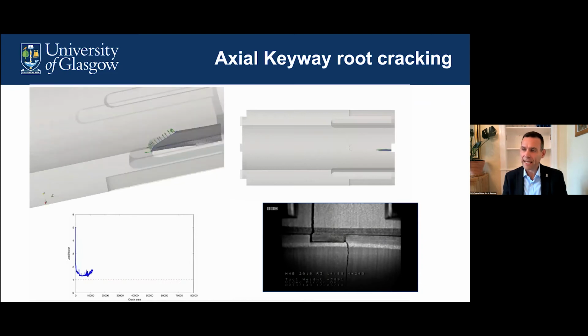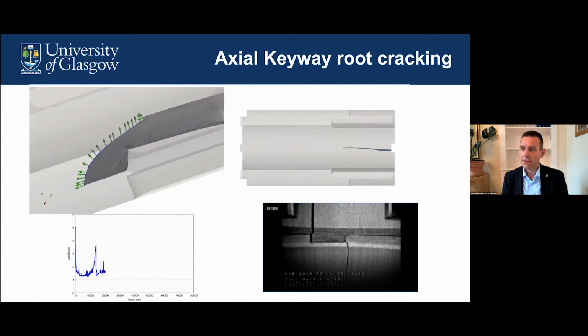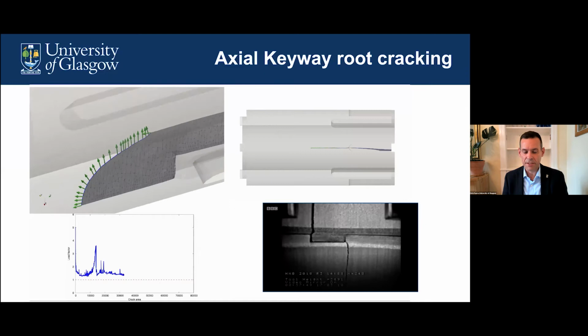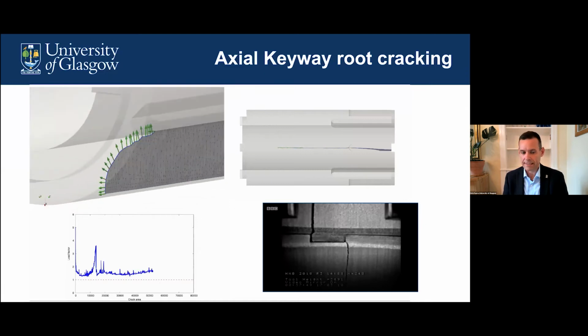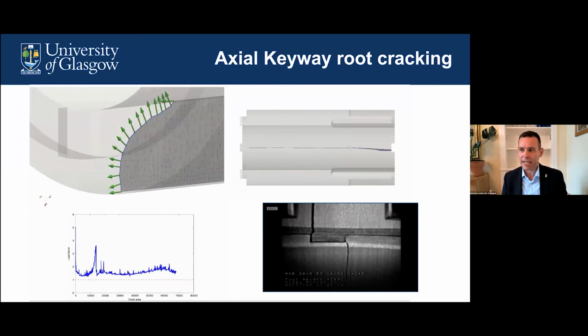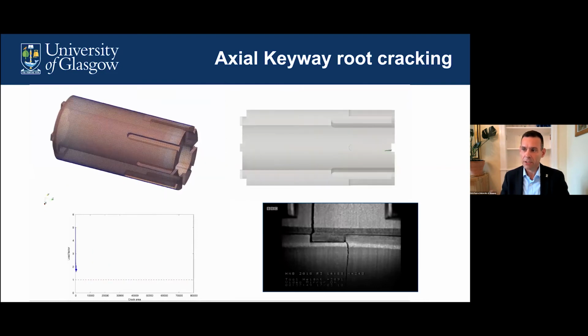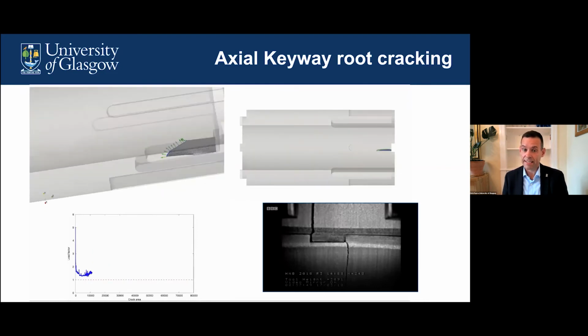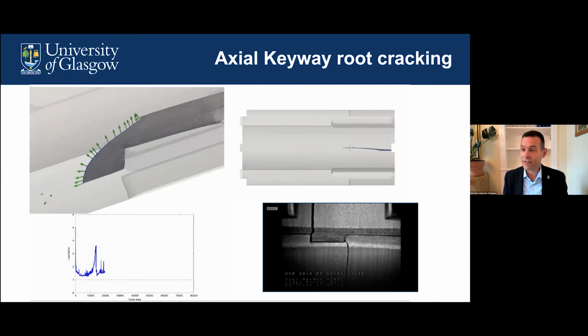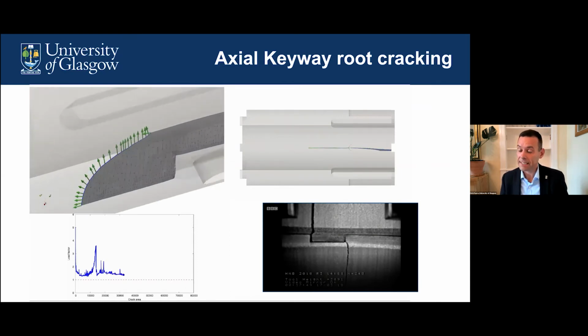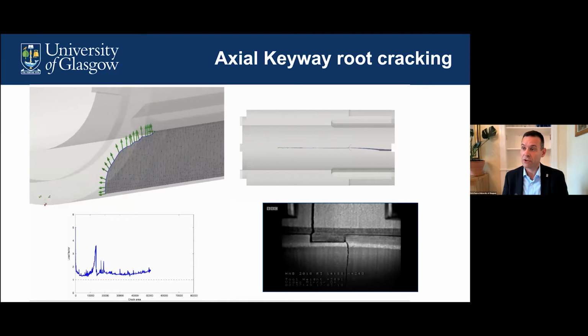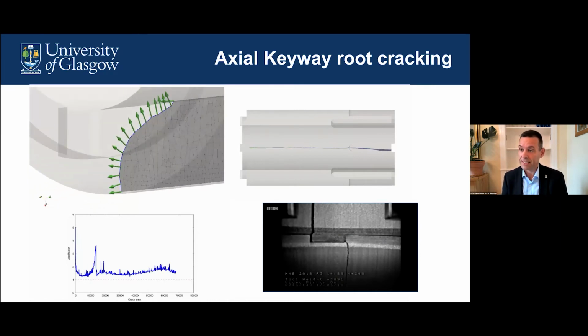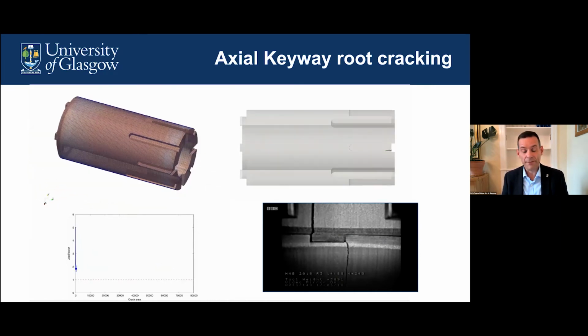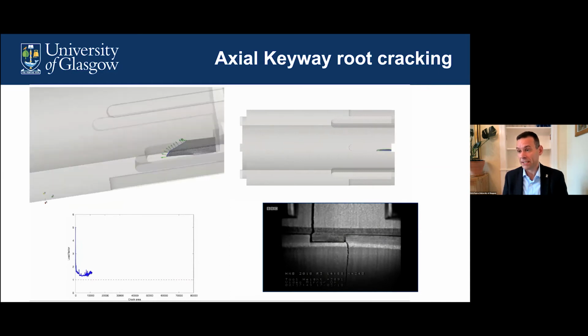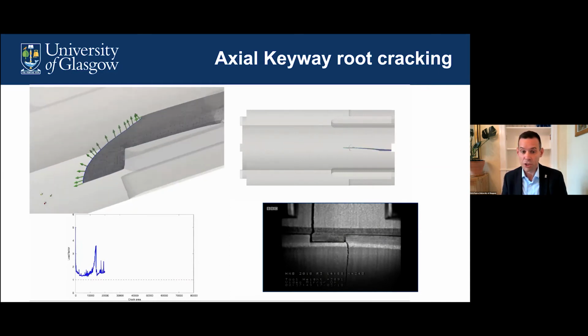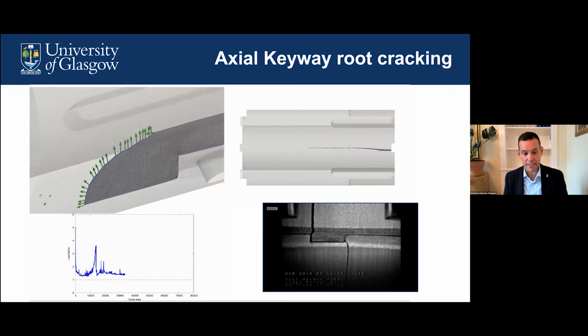On the top right-hand side is the outside view. And on the bottom left, I'm plotting the load factor on the vertical axis versus the crack area on the horizontal axis. So what we're saying is, to what extent do we have to scale the load factor in order to get this crack to propagate? If it's above 1, we have to scale the internal stresses greater than the stresses predicted as a result of aging. If it was less than 1, then we'd be predicting that cracking would have already happened at that age or that dose of irradiation.